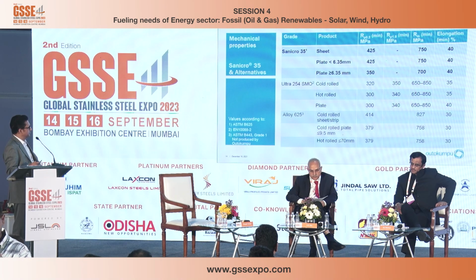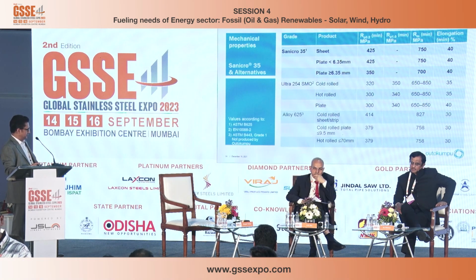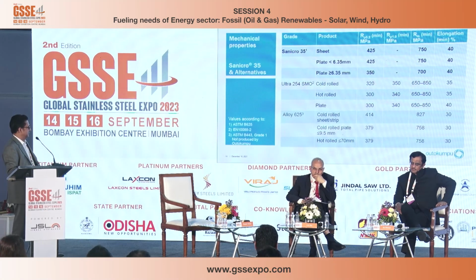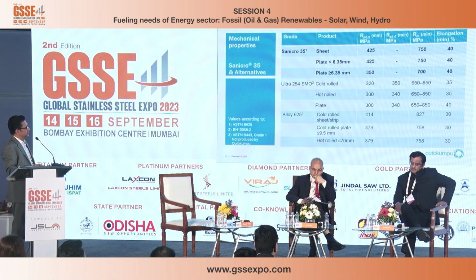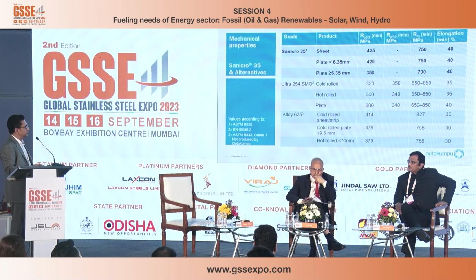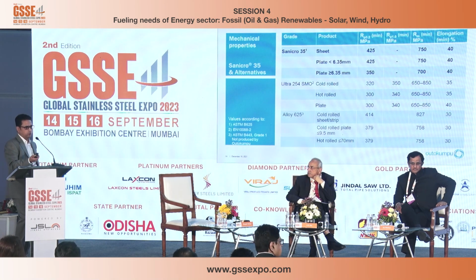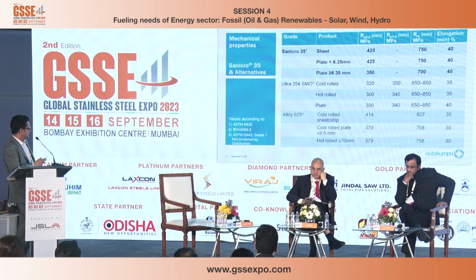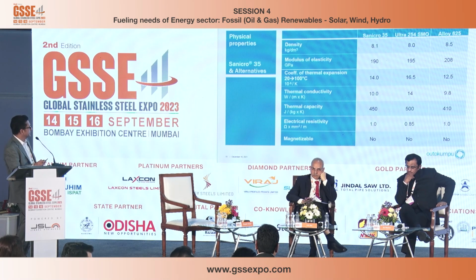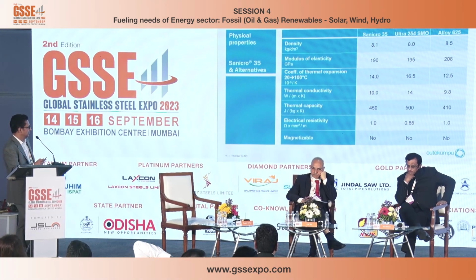Now coming to the properties, let's compare only Sanicro 35 and 625. First thing is the RP yield strength of the material. In alloy 625, you're talking about 379 in the hot rolled condition, whereas in Sanicro 35 it is 350, almost comparable, and the cold rolled form is also more or less comparable. Mechanical strength is also more or less comparable, but when you talk about the elongation of the material, in 625 it is 30%, whereas in Sanicro 35 it is 40%, which means you are able to fabricate or form Sanicro 35 much more easily. And these are the standards mentioned. Looking into the physical properties, the density of Sanicro 35 is less than alloy 625, and the modulus of elasticity is more or less comparable. More or less everything is comparable.